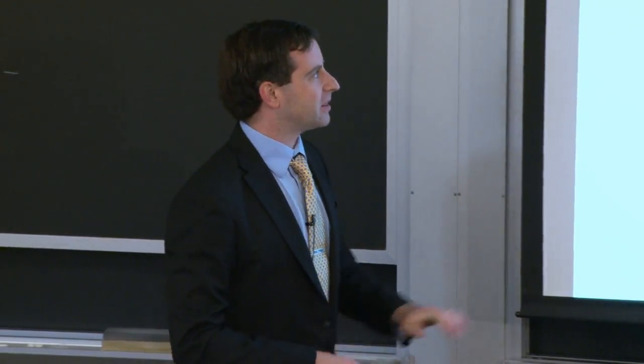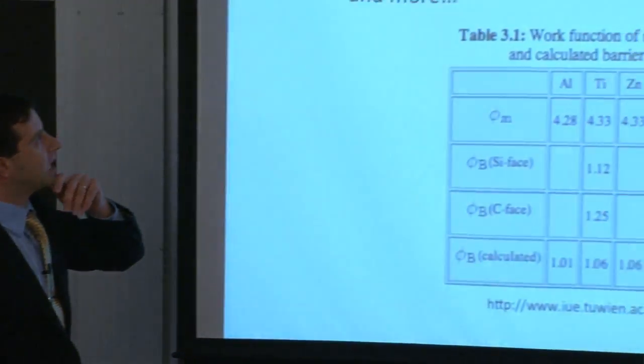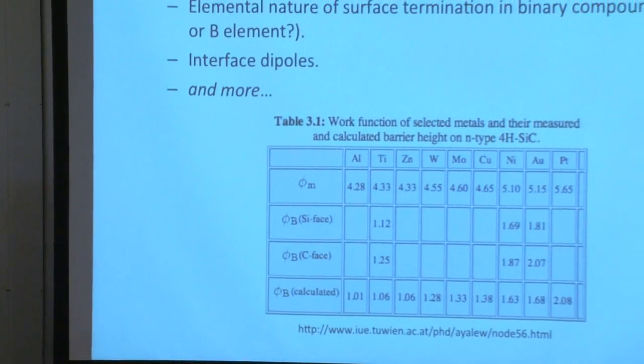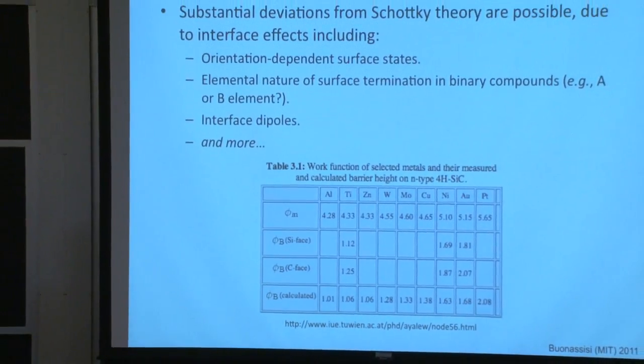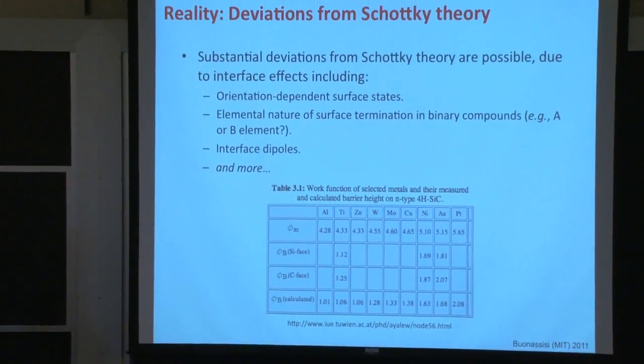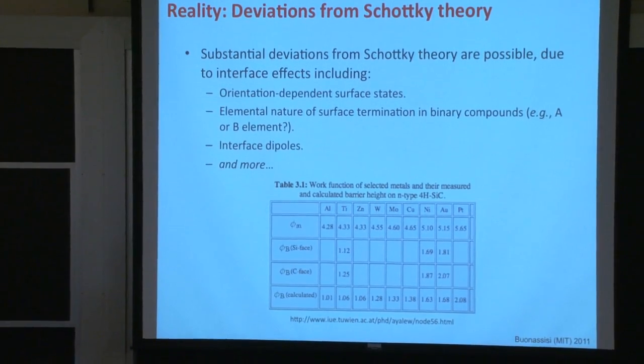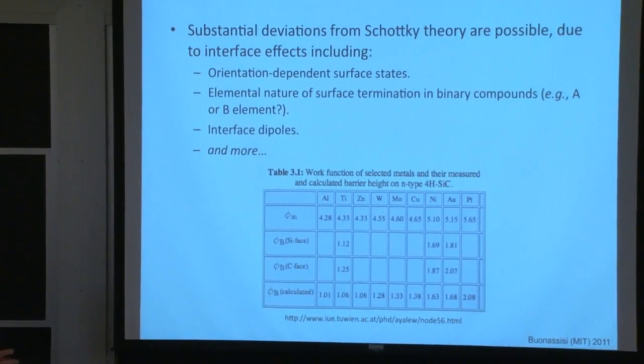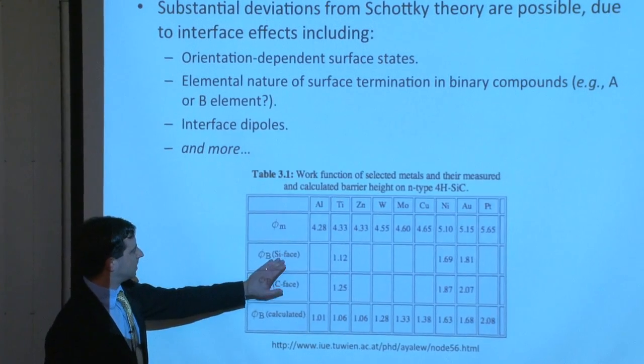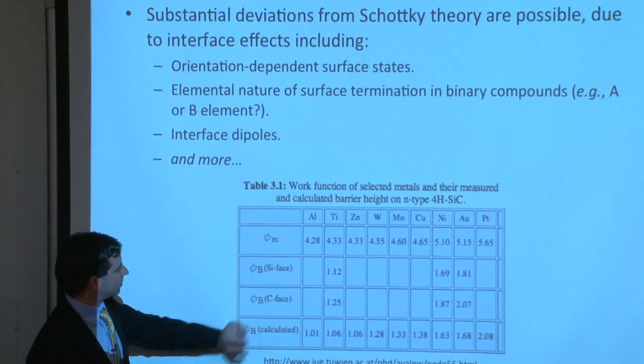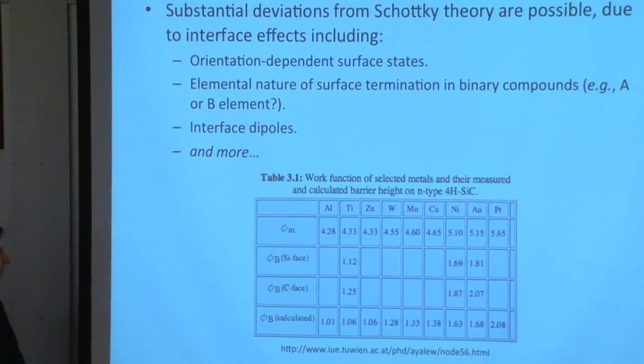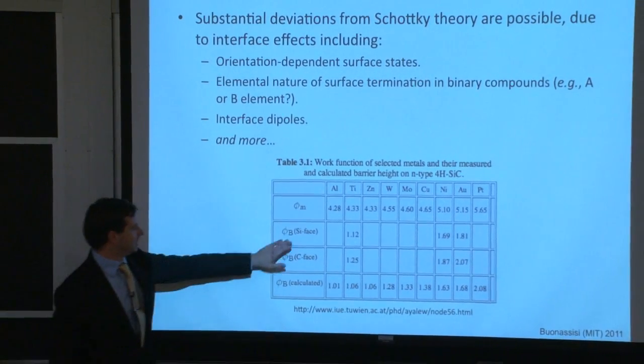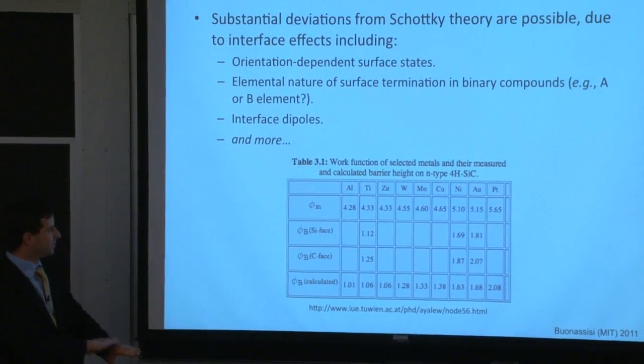We'll get to that in a few slides as well. So this is meant to shine light on a much broader picture, which is to say that there can be substantial deviations from Schottky theory at the interface. And some of the effects are due to orientation-dependent surface states. It could be due to the specific elemental nature of the terminated surface, as we just discussed, whether you're terminating at the silicon row or plane or the carbon plane.